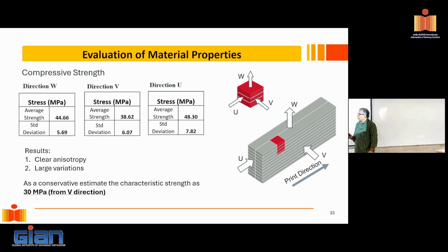Suppose I can translate whatever is the time of transit into some strength measure. And we know that the U direction is always the strongest, and the V direction is always the weakest, which is basically when you're testing perpendicular to the layers, right? Now, if I keep that orientation in mind, if I can somehow translate these time gaps into strength reduction, then can I still use this?